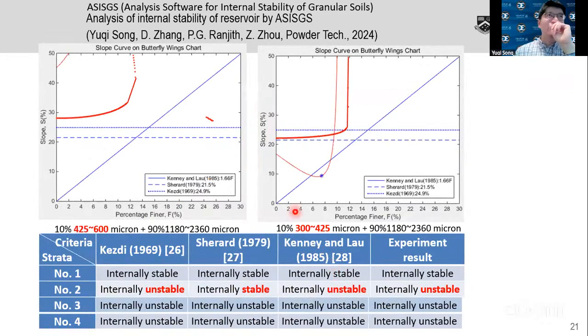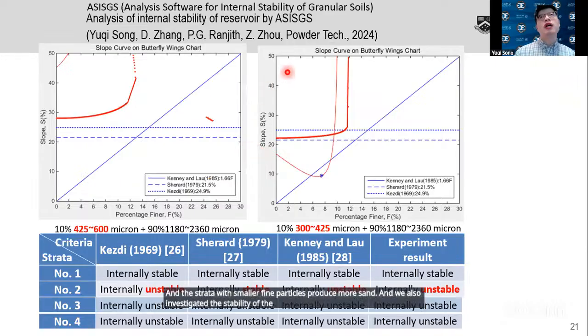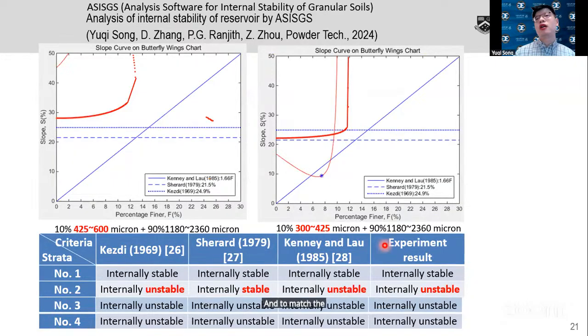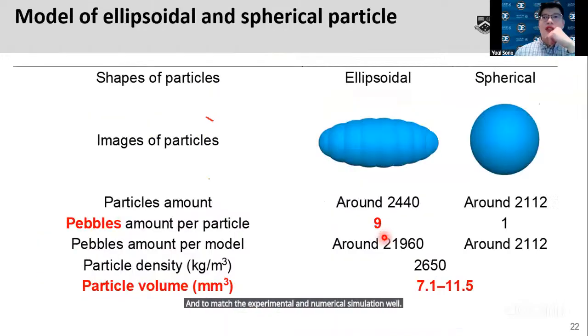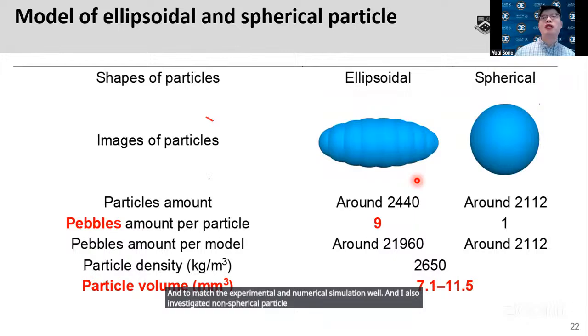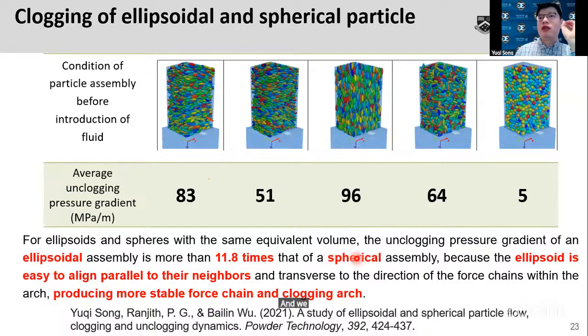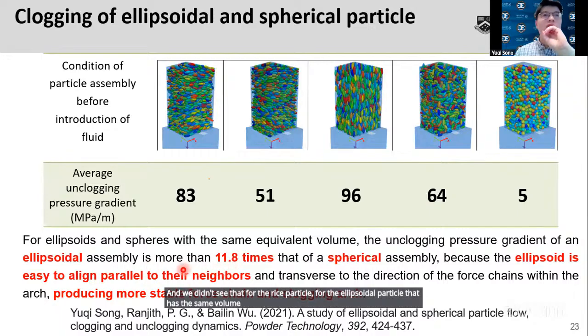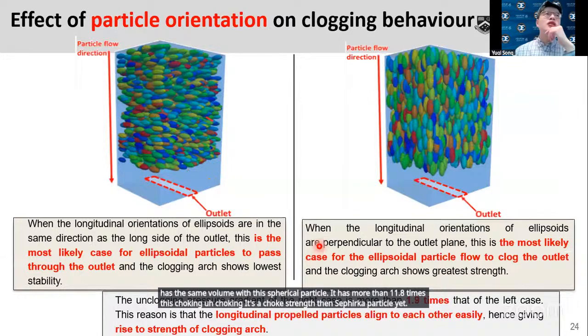We also investigated the stability of the reservoir with a newly developed software called ASISGS, and it matched the experimental and numerical simulation well. I also investigated non-spherical particles, the rice particle, because rice is a very easily obtained particle. That's a typical non-spherical particle. We can see that the ellipsoidal particle, which has the same volume as the spherical particle, has 11.8 times the choke strength of the spherical particle.